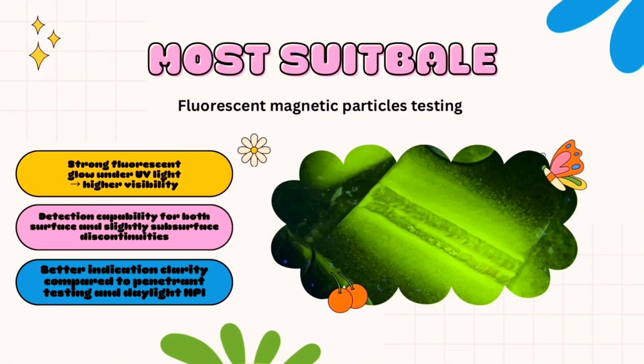Based on the comparison of the results, the most suitable inspection method for detecting porosity in this case is the fluorescent magnetic particle inspection. This method is highly recommended because it provides the highest sensitivity, especially under UV light, allowing small defects such as microporosity to be detected clearly. Therefore, fluorescent magnetic particle inspection is the most effective and reliable method for detecting porosity in this sample.